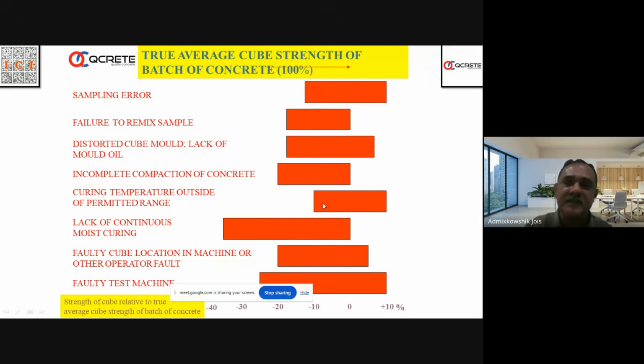Curing temperature outside the permitted range. So concrete mix design is done, and then cubes are cast, and cubes are cured at a standard temperature as per Indian Standard, 27 plus or minus 2 degrees. So when somebody is curing at a different temperature, for example, now in Delhi, the temperature at night may be around 6 degrees or 5 degrees or just below 10 degrees. When the concrete trial mixes were done, the temperature probably was 30 degrees or 25 degrees, whatever it is. Then it was cured at 27 plus or minus 2 degrees. But when you are supplying the concrete, if the cubes are not cured at 27 plus or minus 2 degrees, and are cured at very low temperature, the hydration process is derailed.